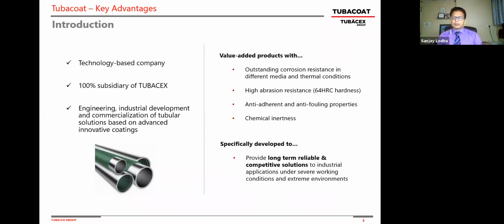With this multiple complex procedure, we get the Tubacoat technology, which combines silica ceramic-based material along with multiple inorganic metal oxides such as zirconium, zinc, sodium, magnesium, and other compounds, fused into an enamel to give outstanding corrosion resistance in different media and thermal conditions, with temperatures up to 1500 degrees Fahrenheit, and resistance to hydrochloric acid, sodium hydroxide, sulfuric acid, and many corrosive conditions. It also has very high abrasion resistance. The hardness of the coating is 4 times higher.